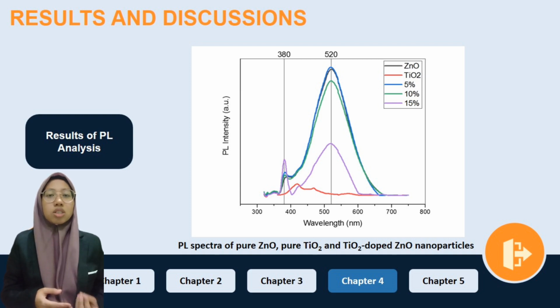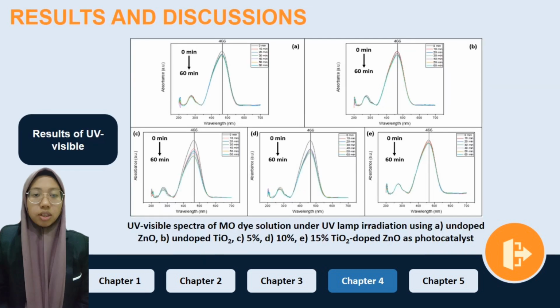The electronic transition from the titanium dioxide shallow donor level to the oxygen vacancy deep acceptor level becomes another mechanism responsible for luminescence, as titanium dioxide is incorporated into zinc oxide nanoparticles. As a result, the visible photoluminescence intensity is enhanced. However, further titanium dioxide content in zinc oxide nanoparticles reduces the visible photoluminescence. That is for the PL analysis.